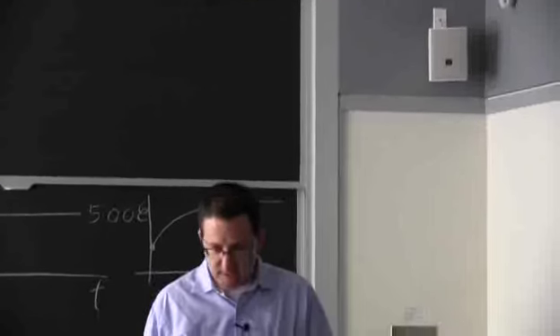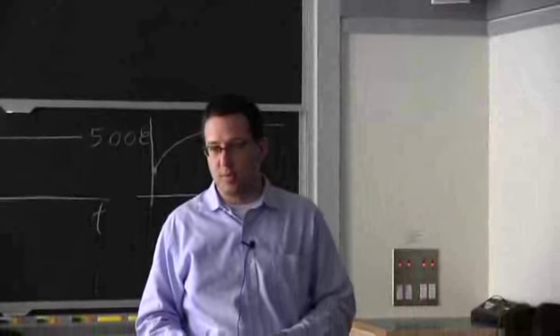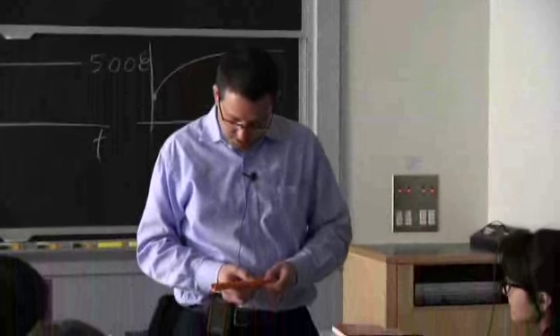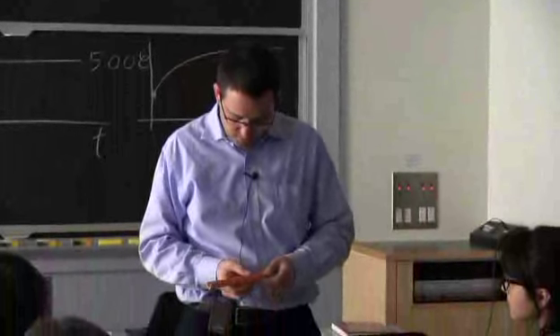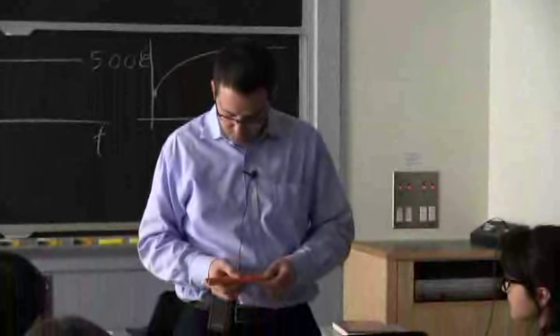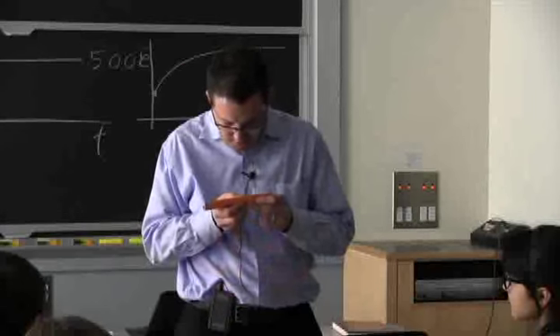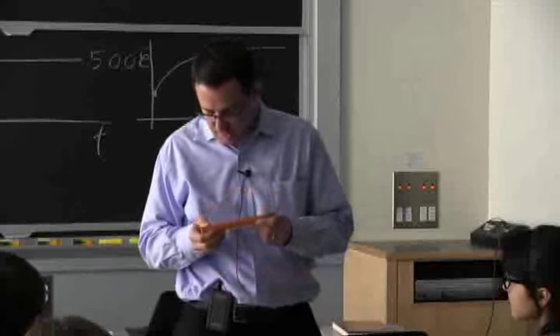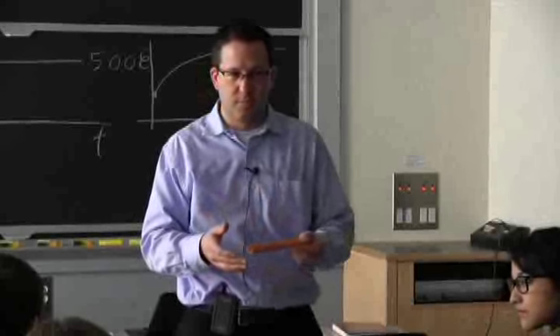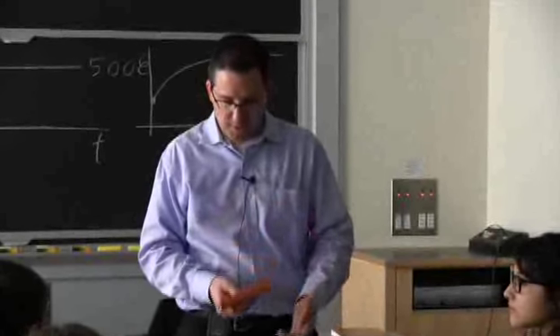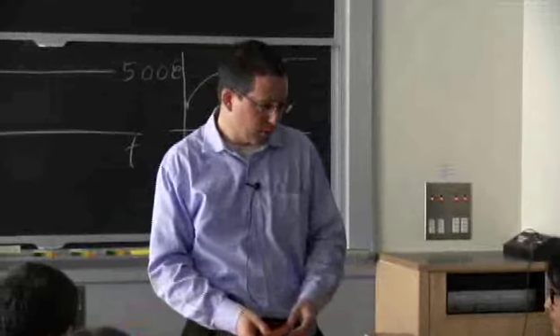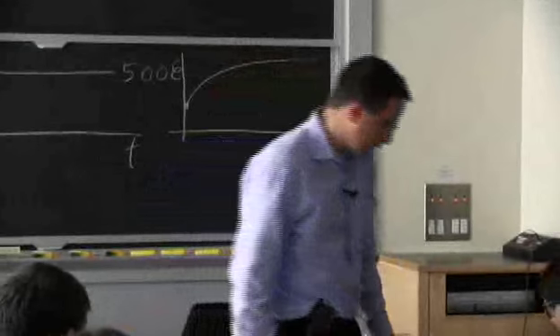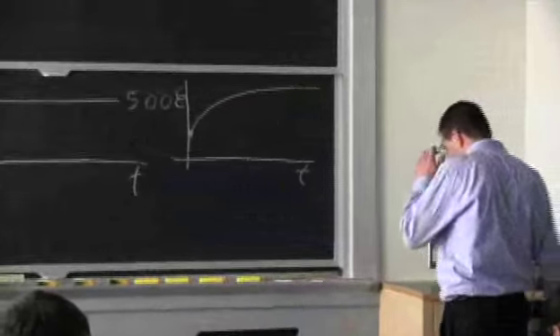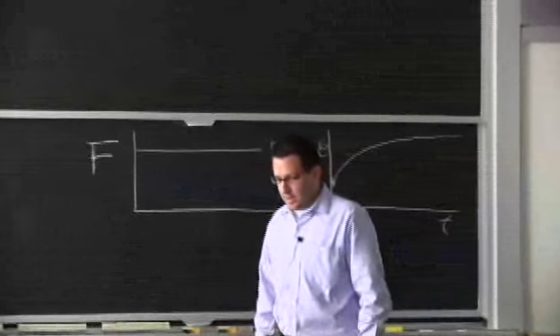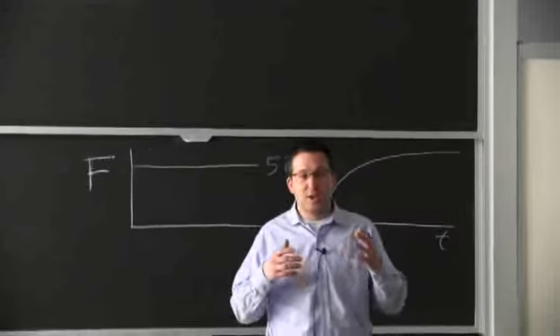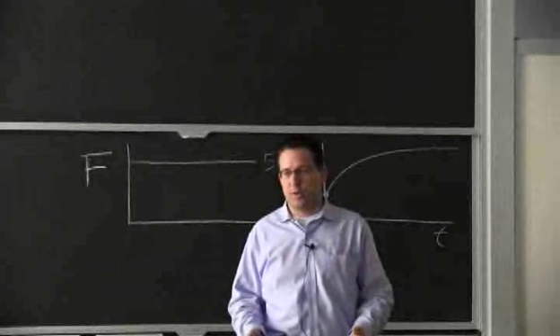Now there's one side that's flat. That's a cut that we made to see half of it. But the upper side, what you see are a lot of small cracks, and probably you'll see the groove from the inside out, and resulted first in leakage and eventually an overall burst of the pipe. So it does happen. A lot of times it happens because you have a bad overall combination of conditions.